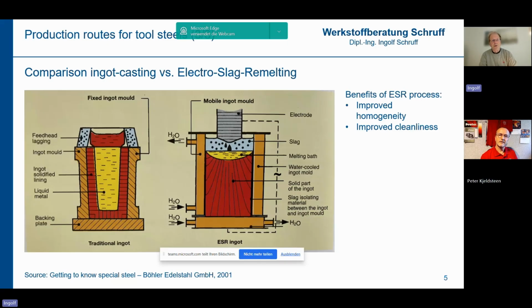Okay. And for several applications, the ESR hot work tool steels get so-called diffusion annealing. That is a heat treatment in the temperature range of 1260 to 1280 degrees centigrade, where these solidified ingots are kept at that temperature for, depending on the cross section, 30 to 40 hours. That is for what reason? That is because the